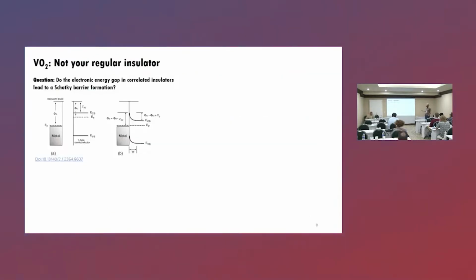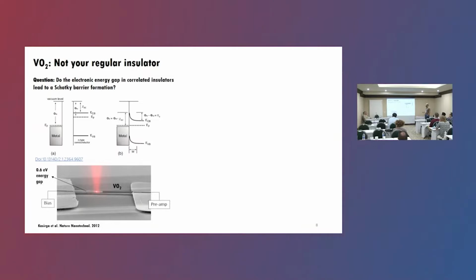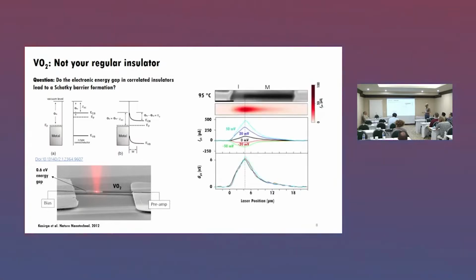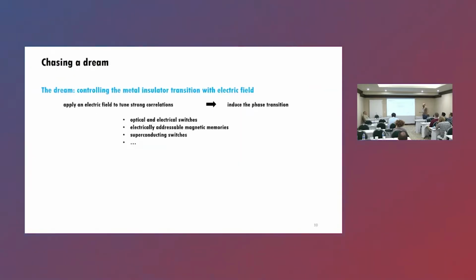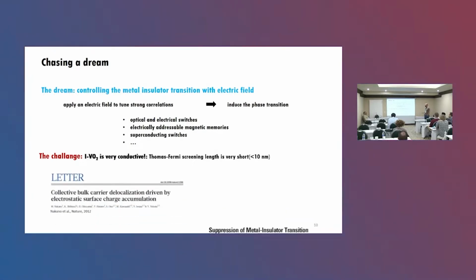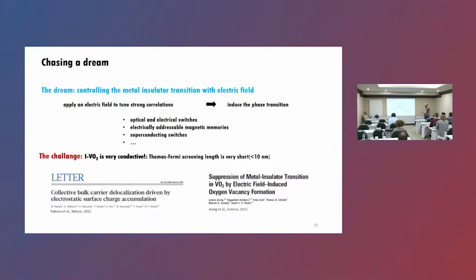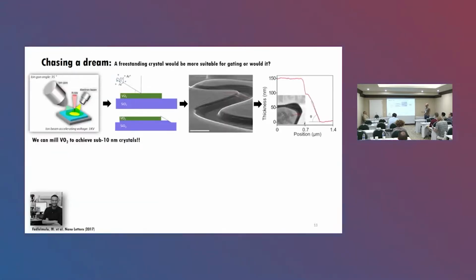And the insulating phase, if you look at it, is not a regular insulator. We also studied that in the past, and we demonstrated that it is not your regular insulator. This is somewhat expected. And obviously, the dream here is controlling this phase transition using an electric field. The problem is that people tried it really hard, but the Thomas-Fermi screening length is very short, so it's quite difficult to modulate. But I took my shot on this one as well.